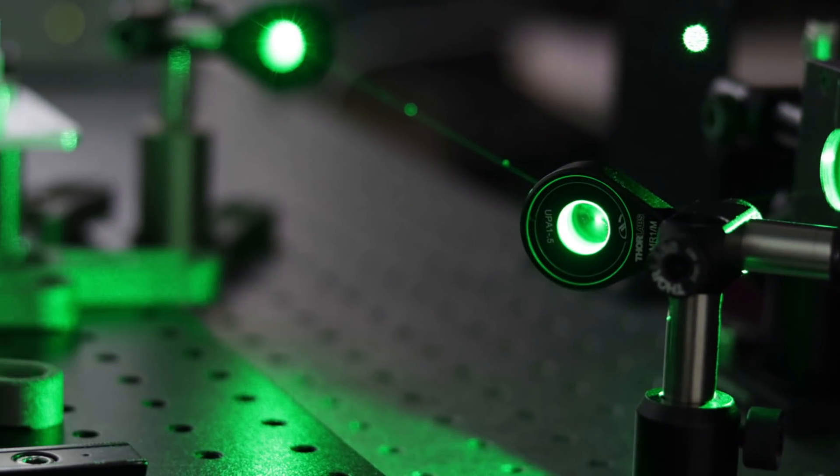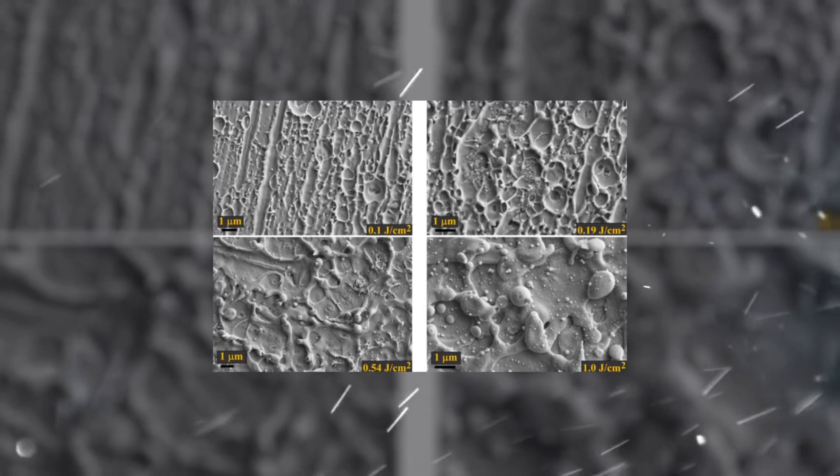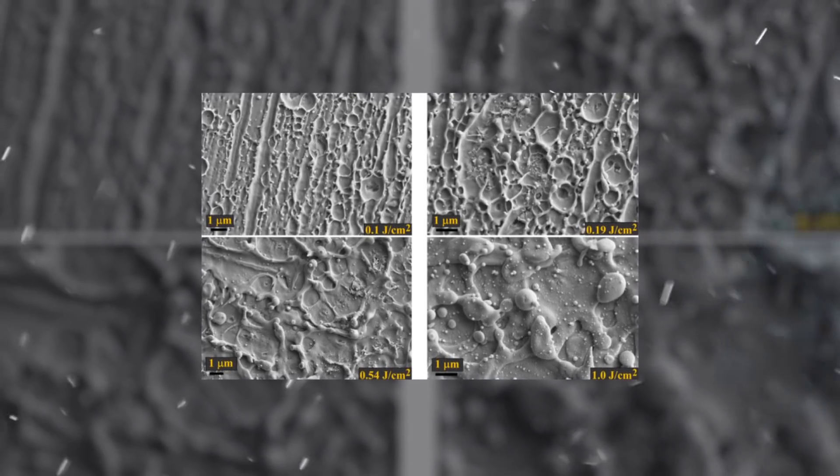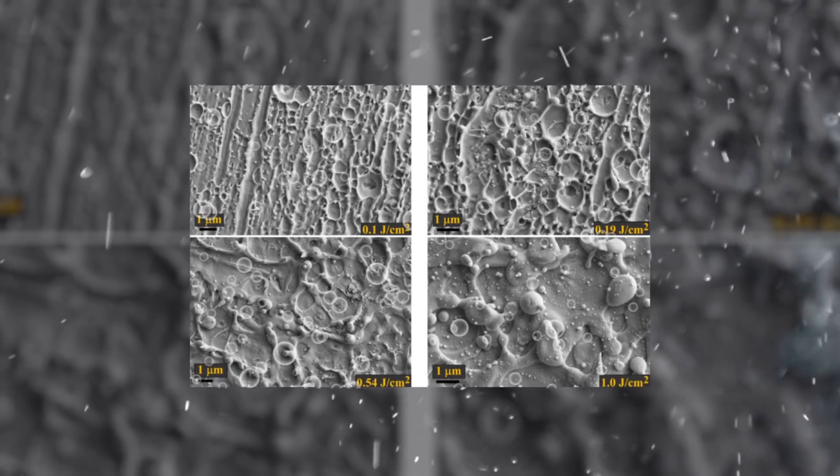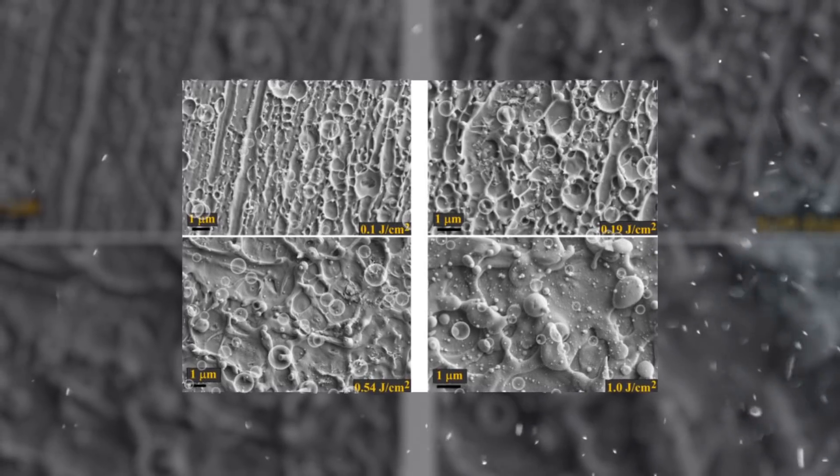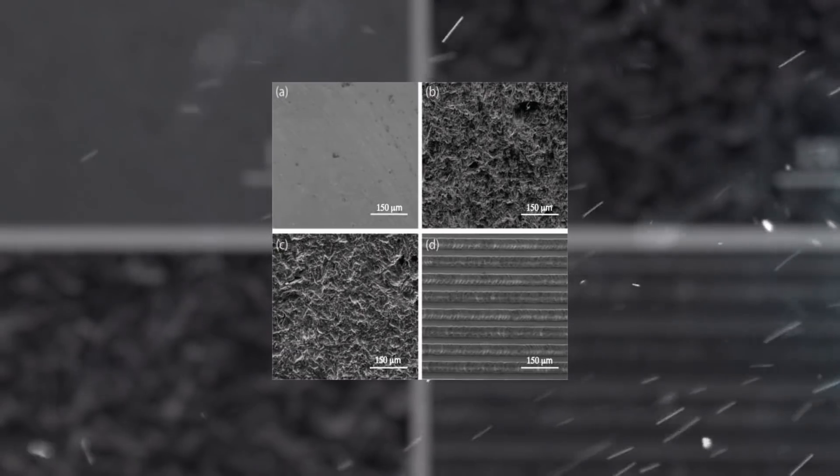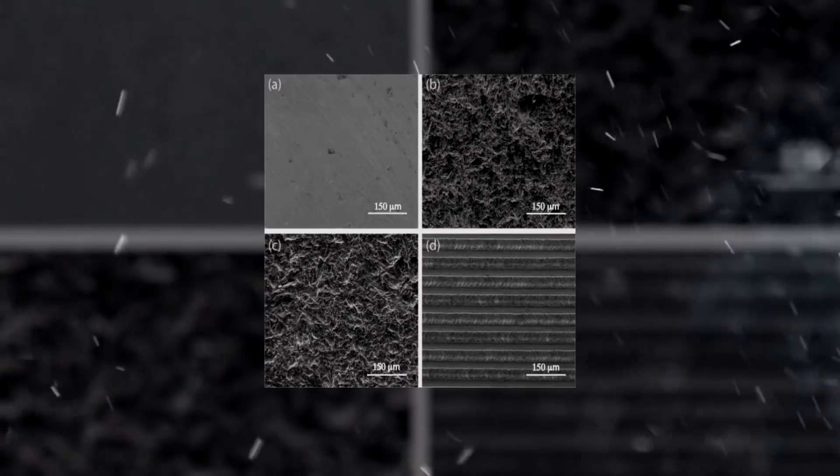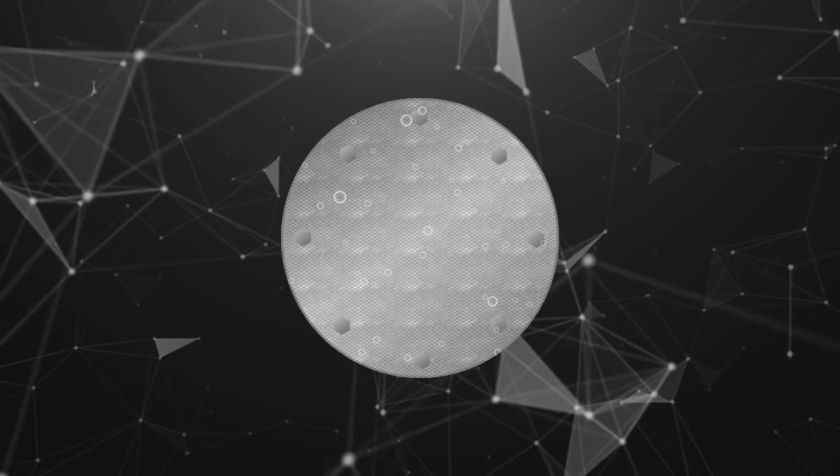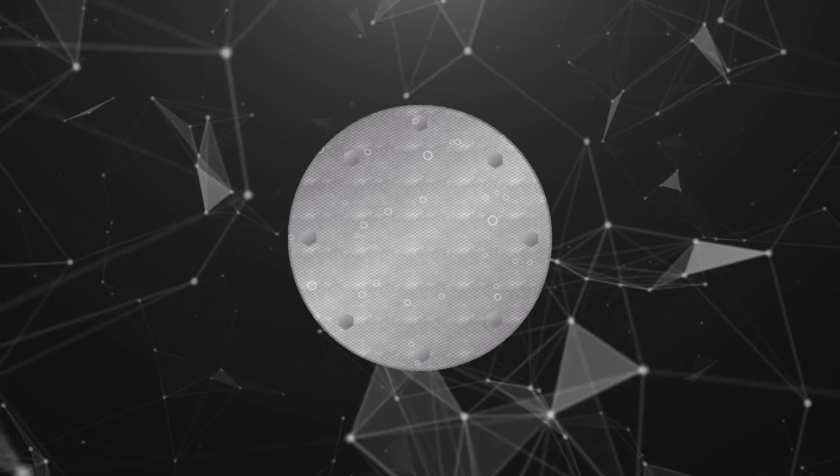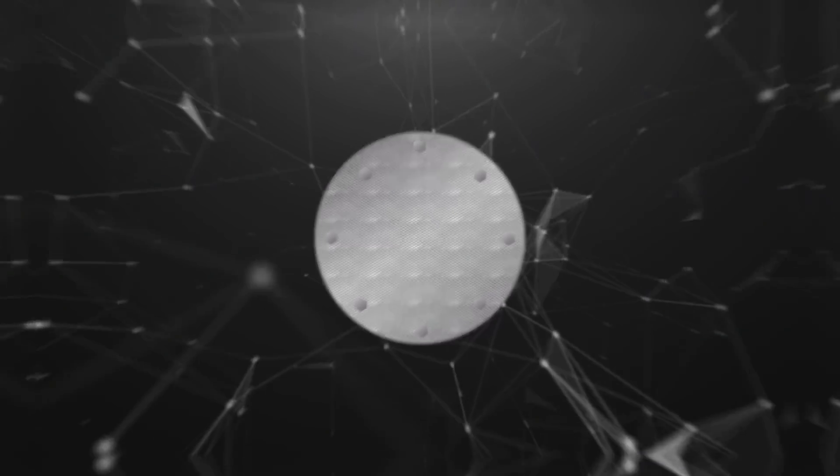Laser manipulations with the structure led to the formation of nanoscale patterns on the surface, which trap air and hold it, preventing the metal from sinking. But the researchers found that the effect doesn't last long. Over time, the material lost its air reserves.